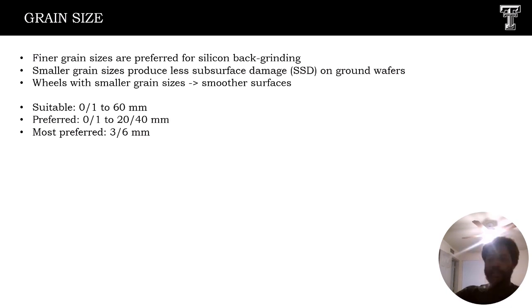Now we're moving on to grain size. It might sound small, but it's a very big deal. Finer grain sizes like 3 to 6 microns are preferred for back grinding silicon wafers because smaller grains mean smoother surfaces and less subsurface damage. Coarser grit removes material quickly but leaves scratches, while finer grit gives a polished finish. That same idea is what's applied here.